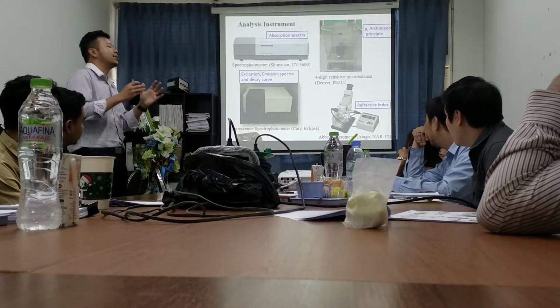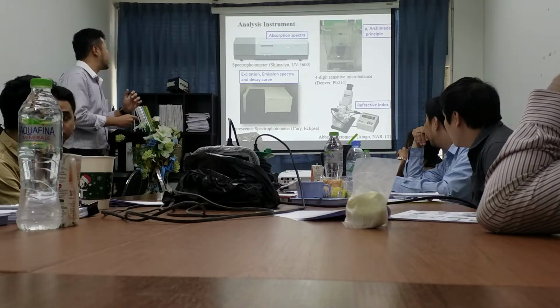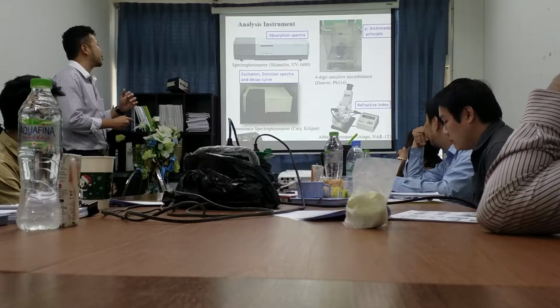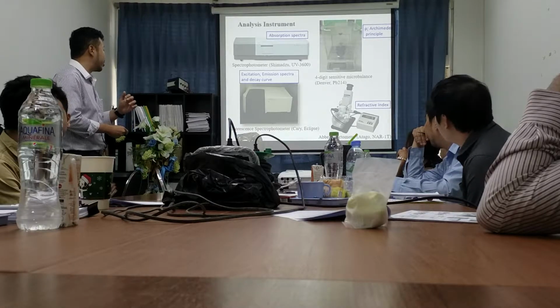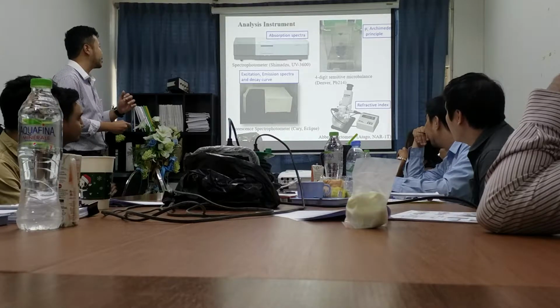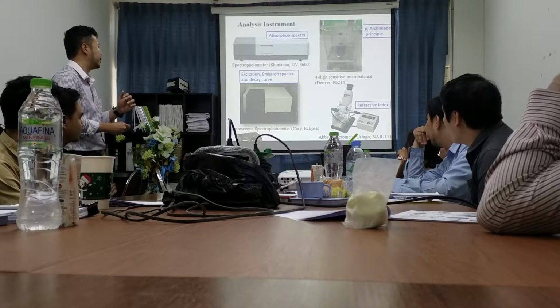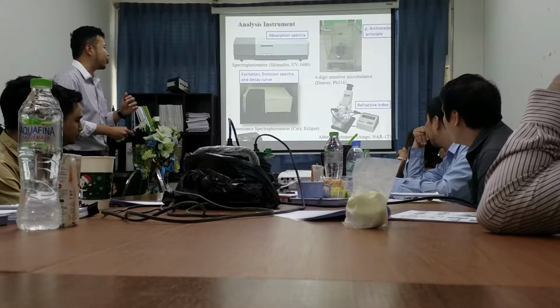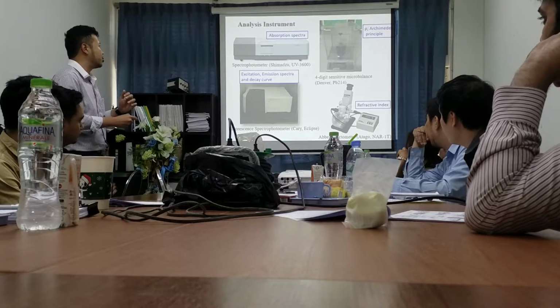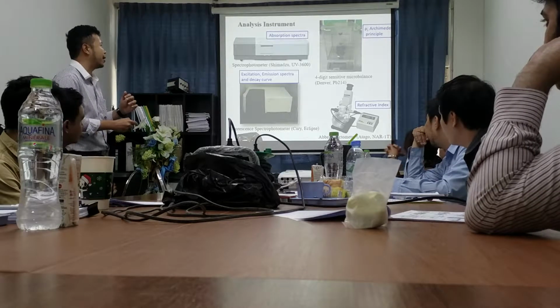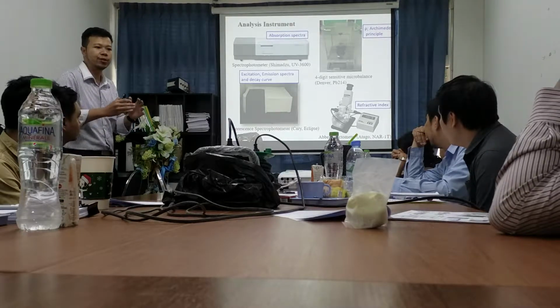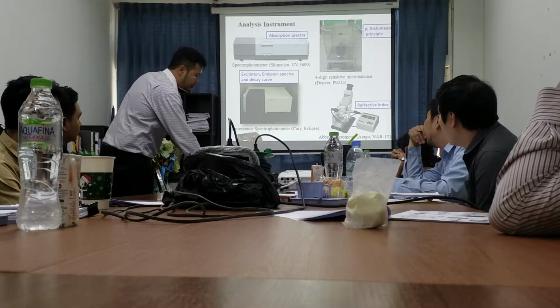This is the analysis instrument. We use the spectrophotometer for absorption spectra, fluorescence spectrophotometer for excitation and emission spectra and decay curve, an Abbe refractometer for refractive index, and a 4-digit sensitive microbalance for density measurement using the Archimedes principle.